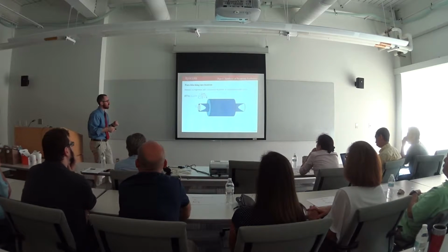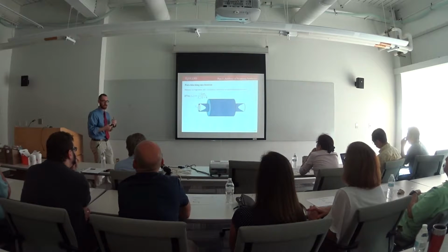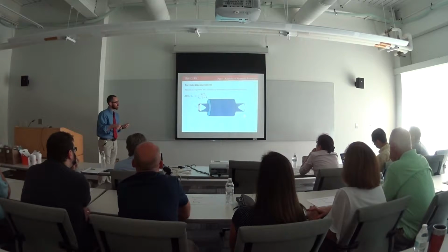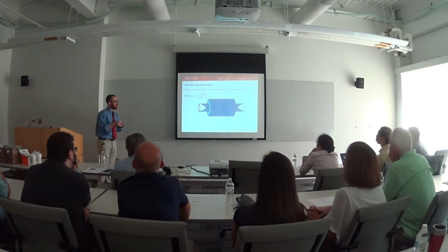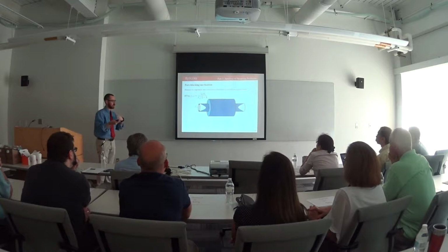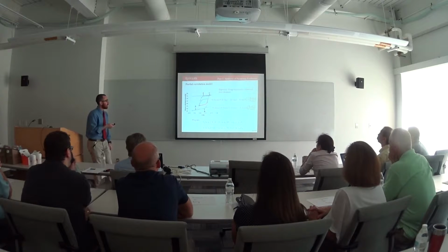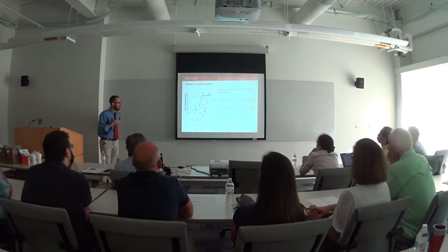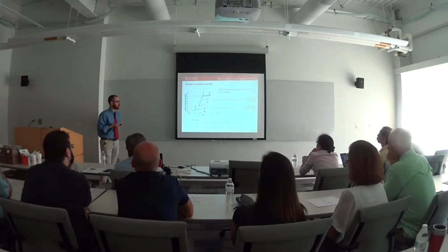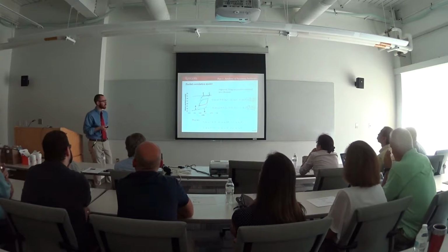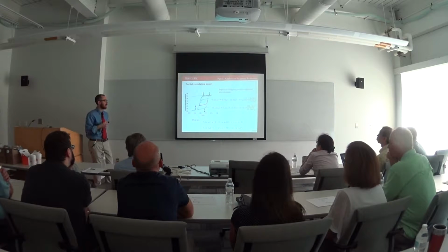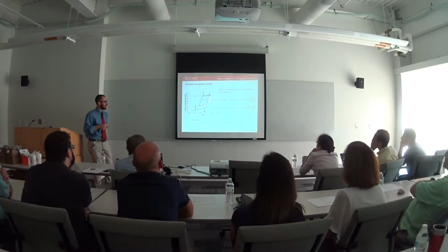However, on desorption, the evaporation from this big pore is going to be delayed because these smaller necks have to evaporate at a much lower pressure than the big pore would. This leads to a delay in your overall evaporation from your pore system. So the first result of this particular piece of work was developing a theory for the fraction of unfilled pores in these partially correlated systems. And what we developed was this theoretical model called the partial correlation model, which allows us to better approximate the scanning curves of partially correlated materials.